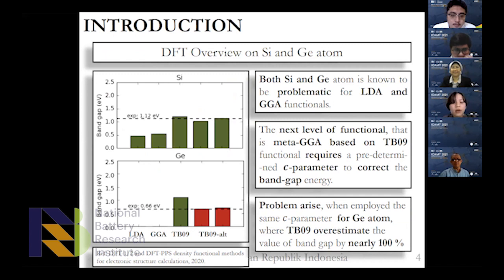So a lot of experimental study has been carried out for this system. However, not so much from the theoretical viewpoint, specifically density functional theory calculation. One of the main hurdles is the fact that germanium is a very notorious case in DFT calculation. Common functionals such as LDA and GGA cannot show an insulating band gap, while the more advanced ones such as meta-GGA under TB09 formalism show an inconsistent value of gap energy.